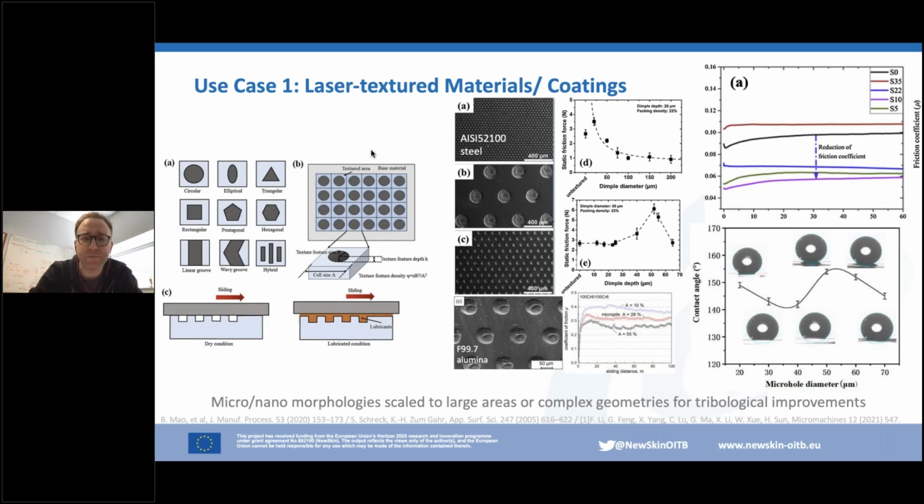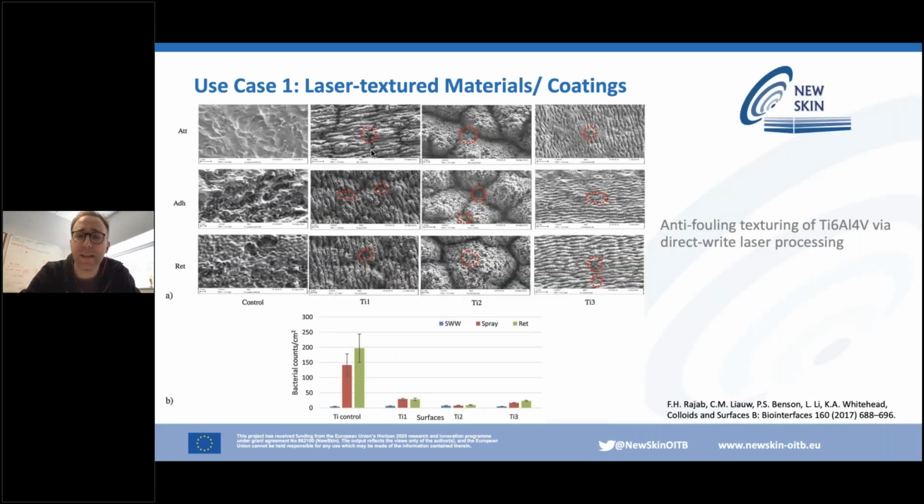Another one for anti-fouling looks at very rough surfaces that have very fine micron or 10 micron sizes. And this reduces organism attachment. This shows a Ti-6-4 surface that was textured using a variety of different micro-sized surfaces. And overall, depending on the attachment technique examined in the lab, across the board, there was a very high reduction in the fouling of the surface.